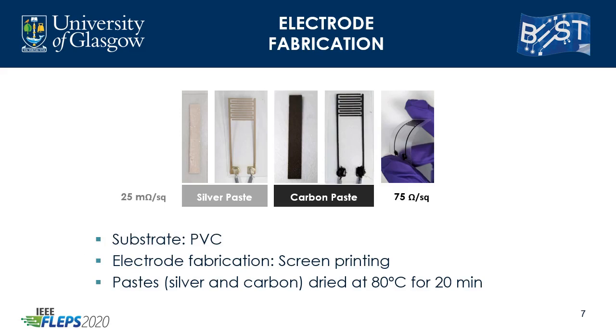We chose screen printing as our fabrication technique due to its direct, easy fabrication steps. We used PVC as the substrate to offer some flexibility and used commercial pastes. The sheet resistivity was much lower in the silver paste, however both values were acceptable. The pastes were dried at 80 degrees Celsius for 20 minutes and 2 different designs were used. The strip was used for cyclic voltammetry and differential pulse voltammetry studies, together with commercial reference and counter electrodes, while the interdigitated structure was employed in the electrochemical impedance spectroscopy study. To minimize interference, we decided to use the same carbon paste on the electrical connection of the carbon electrode.